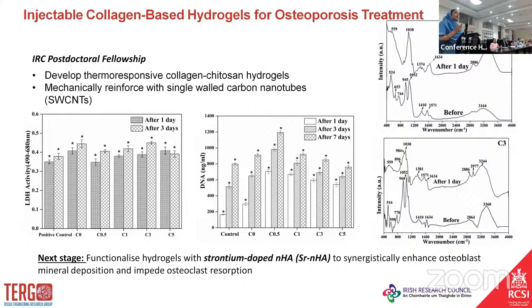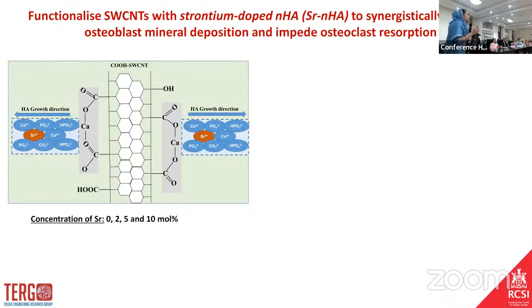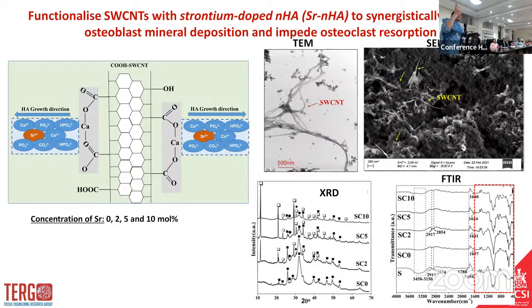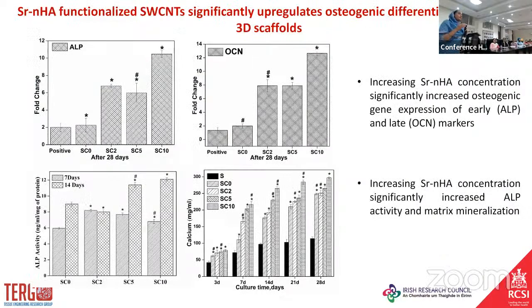hydrogels. In the next phase, we further functionalized single wall carbon nanotubes with strontium hydroxyapatite, because we want to see the effect of therapeutic ions on the hydrogels. This is the structure of the single wall carbon nanotube, which was carboxylic acid functionalized, and we further functionalized it with strontium hydroxyapatite. We studied TEM and SEM and found overlapped single wall carbon nanotubes with strontium hydroxyapatite. After that, we checked its biocompatibility with rat MSCs, and we looked at ALP and OCN fold change, which are PCR results.